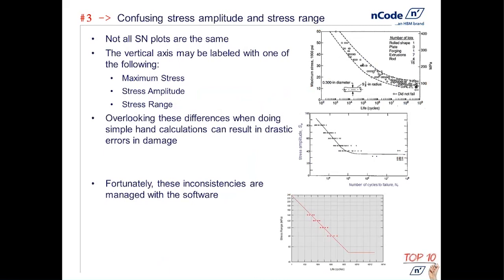We have quite a bit of confusion that comes from looking at the stress-life plots. You may find inconsistencies when looking at plots, particularly if you're looking at some older plots, because they're not all the same. If you look closely on the vertical axes, you'll notice different labels. In the early days, there were a lot of labels that you would see labeled maximum stress — the idea was everybody assumed that we had a mean stress of zero.